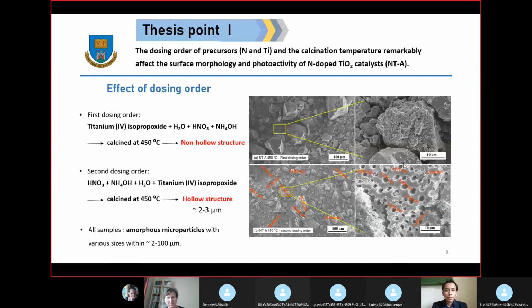This is our first thesis point. The dosing order of the precursors and the calcination temperature significantly affect the morphology and the photoactivity of the catalyst. From this SEM image, we see that in the first dosing order, where we first added the titanium precursor and then the nitrogen precursor, we got a non-hollow structure. But if we change the order, with the nitrogen precursor first and then the titanium precursor, it produces a hollow structure with around 2 micrometer diameter. But all of these materials are of irregular shape, in microparticles of around 2 up to 100 micrometers.